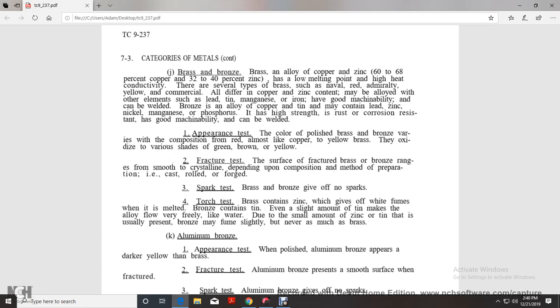Appearance: the color of polished brass and bronze varies with the composition, red, almost like copper, to yellow. Brass oxidizes to various shades of green, brown, and yellow. Fracture test: the surface of fractured brass and bronze ranges from smooth to crystalline, depending on the composition and method of preparation, whether cast, rolled, or forged. Spark test: brass and bronze give off no sparks. Torch test: brass contains zinc, which gives off white fumes when melted. Bronze contains tin, and even a slight amount of tin makes the alloy flow very freely like water. A small amount of zinc is usually present in bronze and may fume slightly, but never as much as brass.